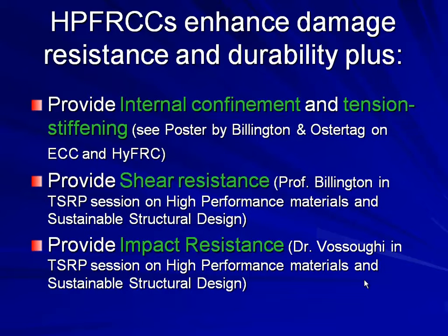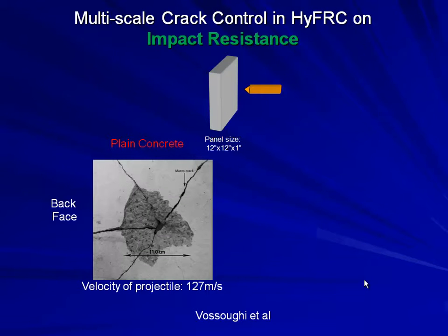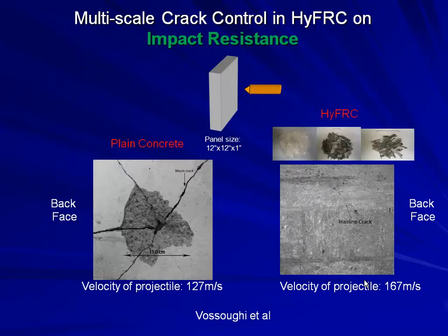I just want to show you one graph, or one slide, of the impact resistance. These are panels. We looked here at a panel size of 12 inch by 12 inch by 1 inch, so very thin panels. When you impact them with a projectile here at 127 meters per second, your concrete specimen is not only damaged, it fractures into pieces. If you look at the hybrid fiber reinforced, this is what you see. There is no damage, you only have very fine hairline cracks, at a much higher velocity of the projectile.